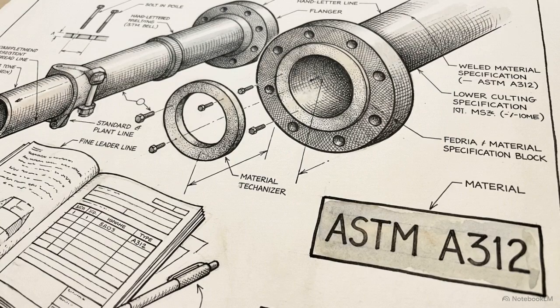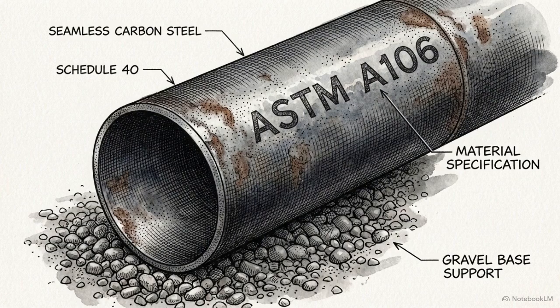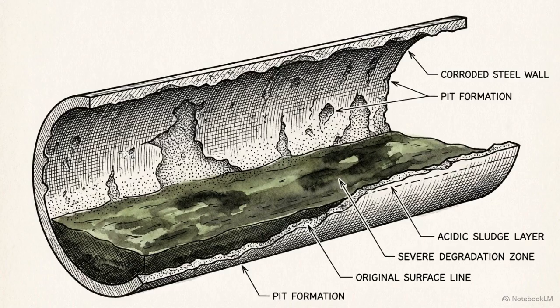The engineering isometric drawing mandates ASTM A312, a high-grade stainless steel. The physical pipe sitting in the yard is stamped ASTM A106, standard carbon steel. Carbon steel is the workhorse of oil and gas piping, but it cannot survive in a wet, highly acidic hydrogen sulfide environment. When sour gas contacts the inner wall of a carbon steel pipe, the acid reacts with the iron. This reaction releases free hydrogen.